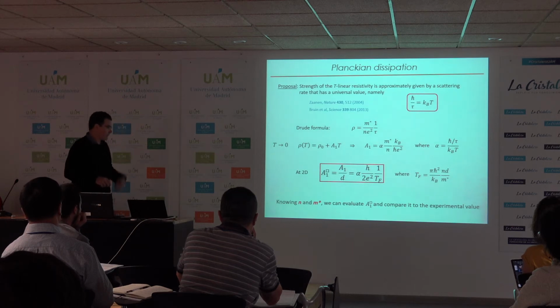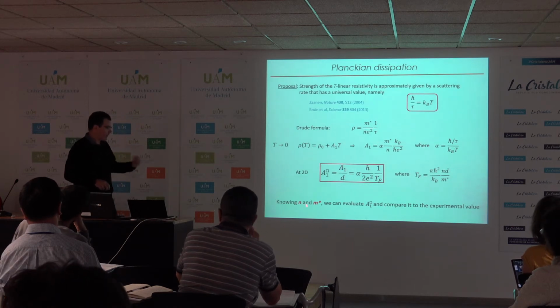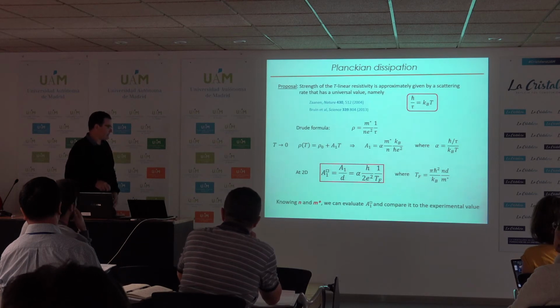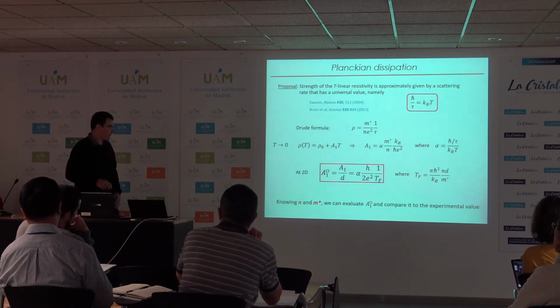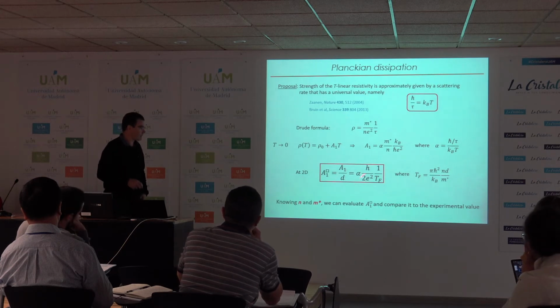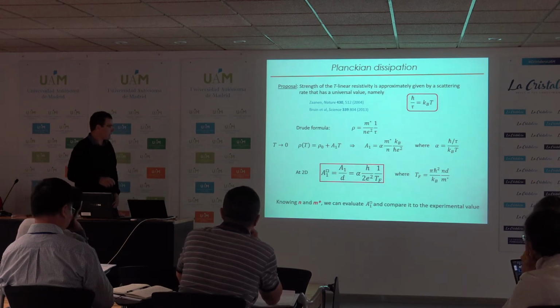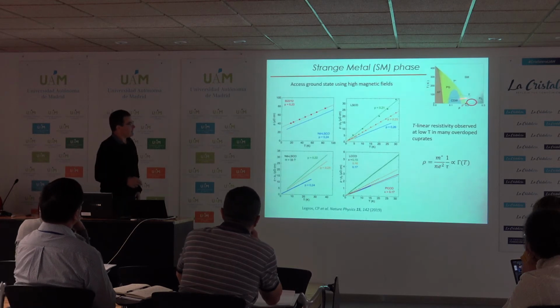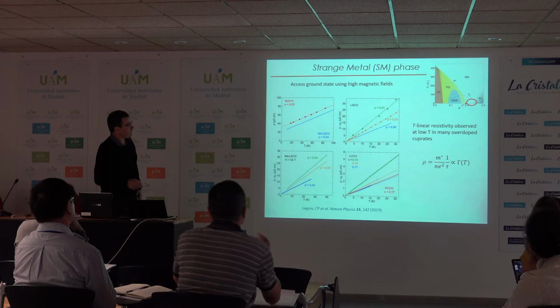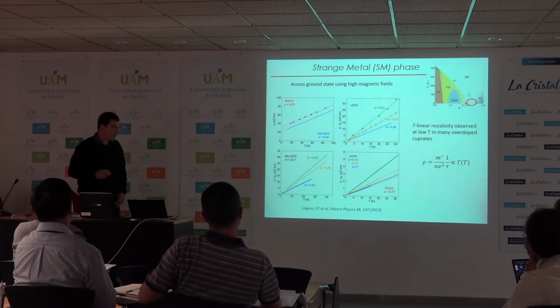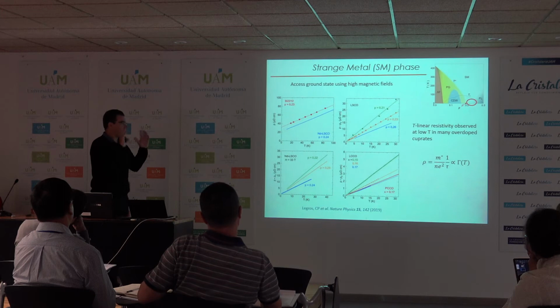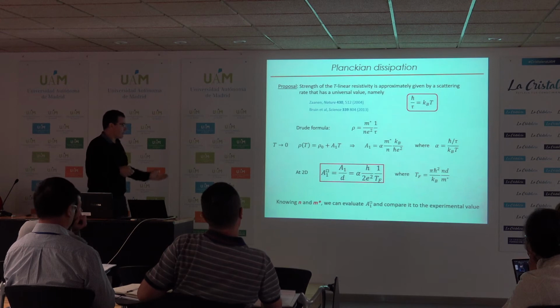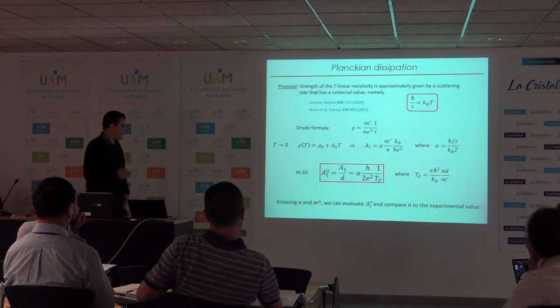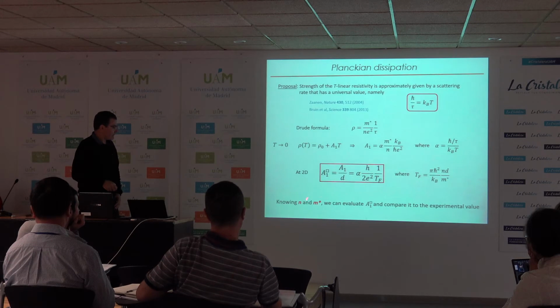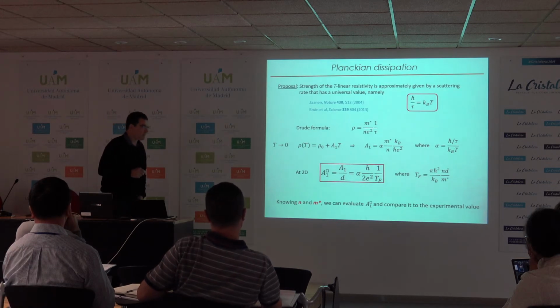So if you can plug the density of carriers and the effective mass into this formula, we can evaluate this alpha coefficient and compare it to the experimental value. Since we are in this overlap region above P star, where we believe in Fermi surface reconstruction, the Fermi surface is given by band structure calculation, and by 1 plus P or 1 minus P depending on the family. Basically, the only parameter we have to put in is the effective mass.